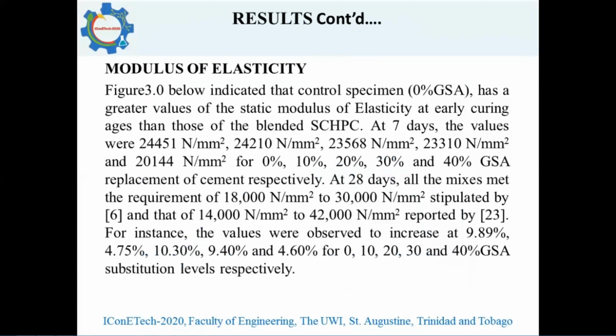The table below indicates that the control specimen has a greater value of modulus at early curing age than those of blended self-consolidating high performance concrete. At 7 days, the values were 24,451 Newton per mm square, 24,210, 23,568, 23,310, and 20,144 for 0, 10, 20, 30, and 40% GSA replacement respectively.